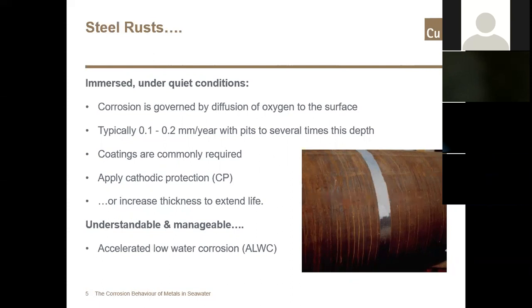The corrosion of steel in seawater is primarily governed by the diffusion of oxygen in the water onto the steel surface. So going back to the previous slides, obviously the oxygen content plays a major part in the corrosion of steel and of cast irons. Research has been carried out in various locations on steels of various compositions. Immersed under quiet conditions, they can have quite predictable corrosion rates of around 0.1 to 0.2 millimeters per year. But they do sometimes suffer from pitting at several times this depth. So the localized corrosion again can be more of an issue than the overall loss of material around the component.